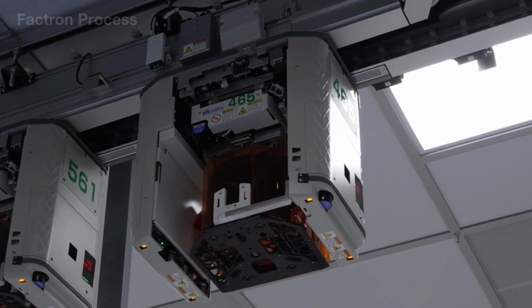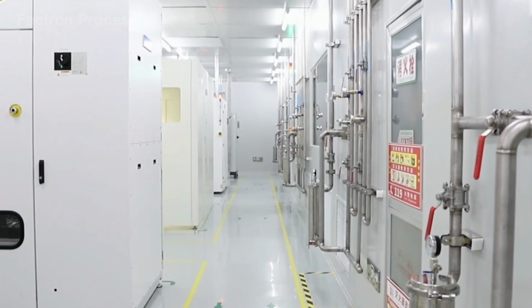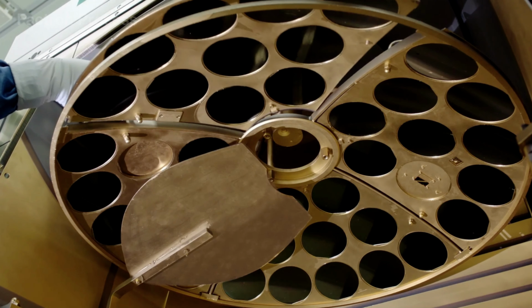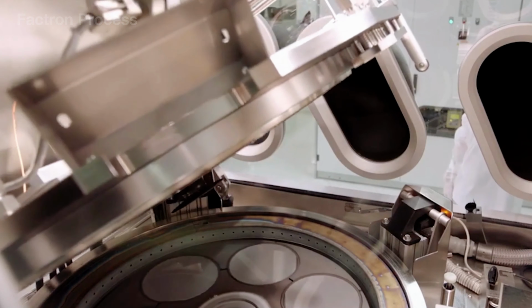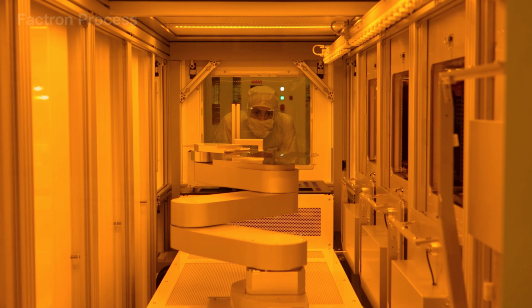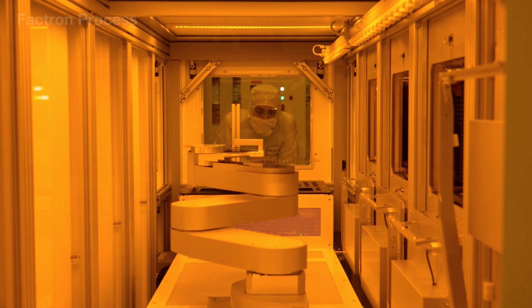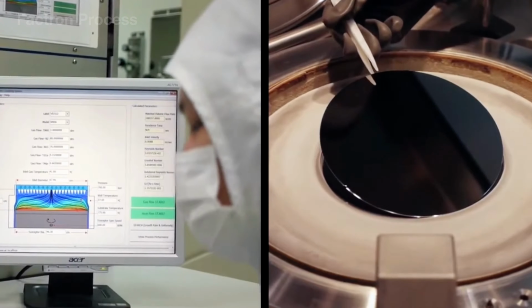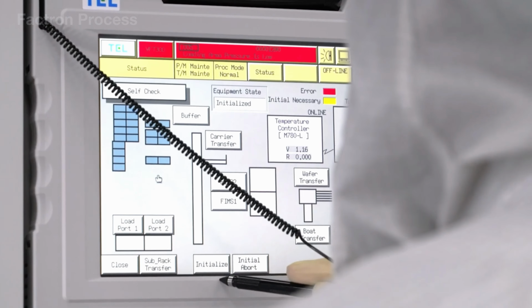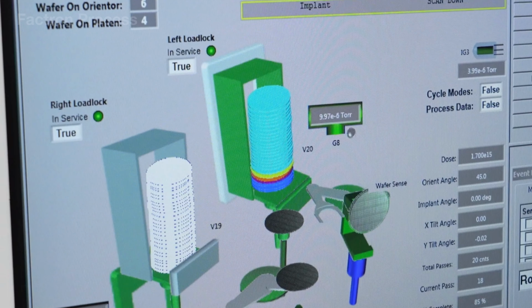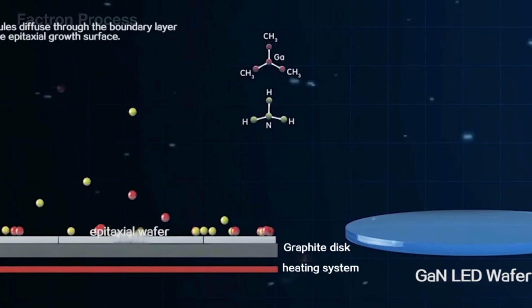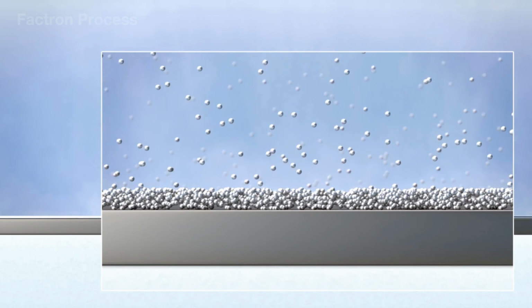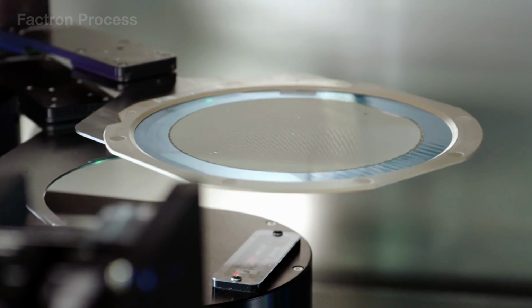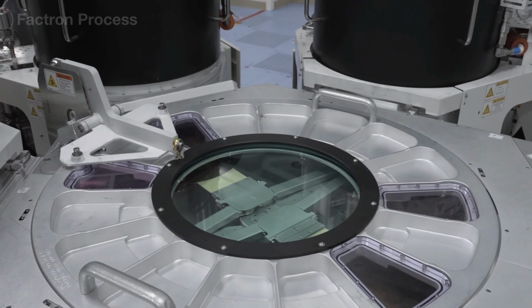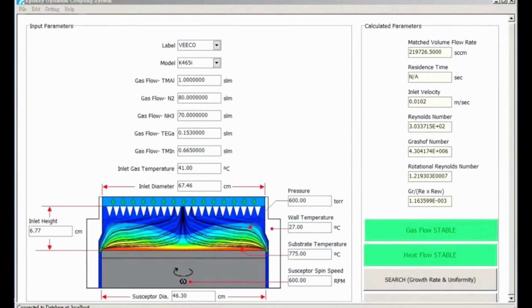Once the design is complete, sapphire wafers are loaded into an MOCVD reaction chamber and heated to approximately 1,832 degrees Fahrenheit. At this temperature, gas compounds containing gallium, indium, and nitrogen decompose, allowing individual atoms to settle onto the wafer surface and form extremely thin semiconductor crystal layers. This process is similar to building an LED chip one layer at a time: a lower conductive layer, a light-emitting region in the middle, and an upper conductive layer. When an electric current passes through the chip, the light-emitting region produces photons. Most remarkably, changing even a tiny amount of indium in the InGaN layer can shift the emitted light from blue to green.